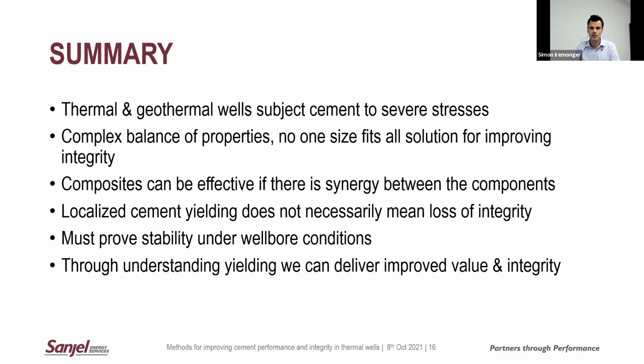Yes. So they are a synthetic organic fiber, not your traditional inorganic materials. We found that those decomposed too readily in a thermal cement matrix. But yes, there is essentially a coating on that allows for good and strong bonding of the cement to that surface, and also for those fibers to be dispersible. Certainly anyone who's dealt with fibers for a lost circulation application, if you're not getting a product that's well dispersible, you can end up making a horribly nasty lumpy cement. So yes, there are coatings on that just to make sure that we get good synergies between the cement and the fiber. Thank you.